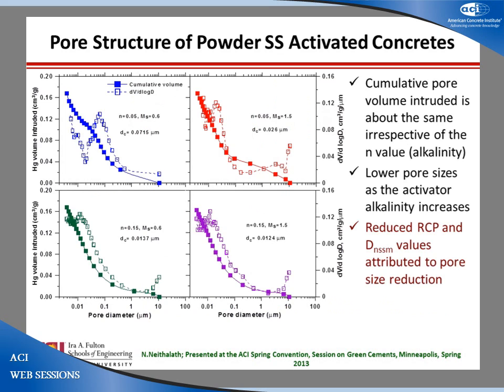Now, the pore structure is quite interesting. What you see here are the pore structures of powder sodium silicate activated mixes at 28 days. You have about 16 to 17% total pore volume for all of these mixes. The pore sizes, though, come down when the alkalinity is higher. From 0.07 microns, the characteristic pore size comes down to about 0.01 microns. So you can say that reduced chloride permeability and non-steady state migration values can be attributed to pore size reduction. I'll show you some proof of this further down.